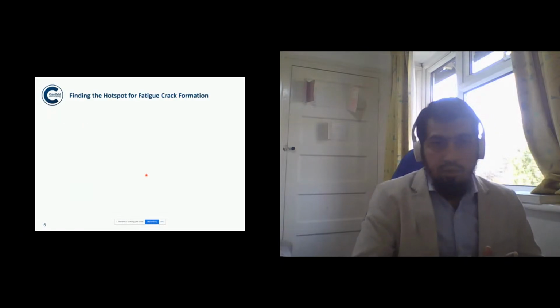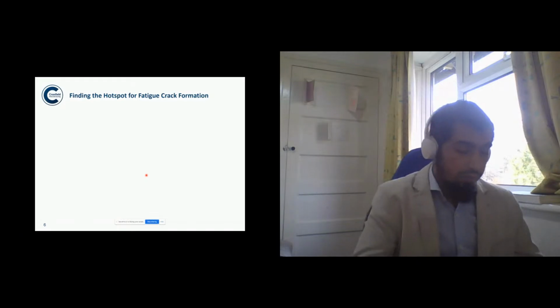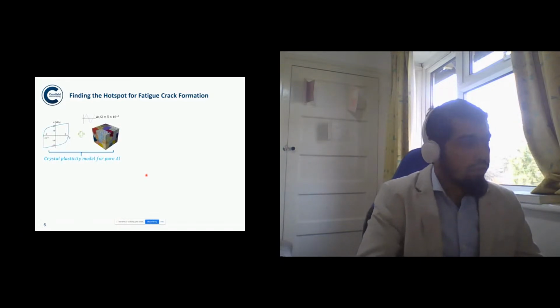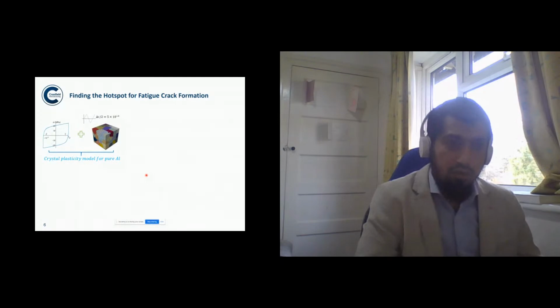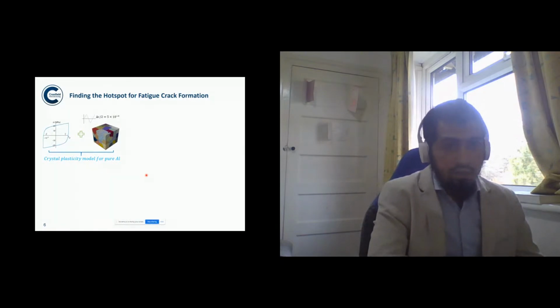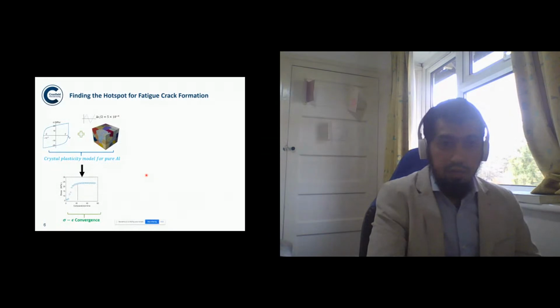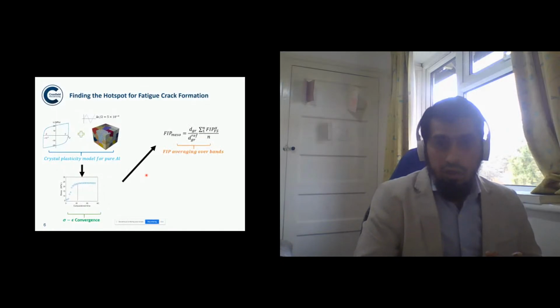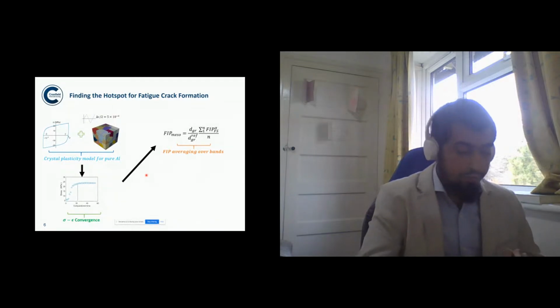So the next step is to find the hotspot where the crack initiates. For this one, we have implemented the crystal plasticity model in Abaqus, and we evolve the model until the stress-strain curve is stabilized. And at that step, we quantify the FIP in each of the slip bands, and we average over the slip band domains.